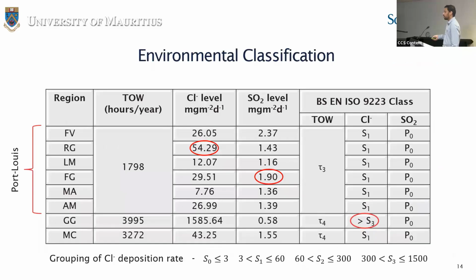A parameter often used instead of relative humidity is the time of wetness, also represented as TOW. This is defined as the duration during which relative humidity is above 80%. The time of wetness values, the chloride deposition rate values, and sulfur dioxide levels have been assigned categories according to BS EN ISO 9223.